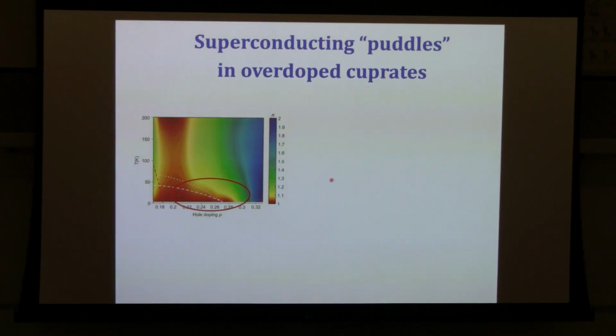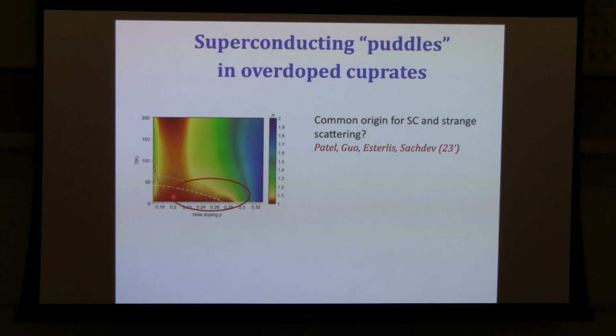The first one is that there's something that's causing the superconducting pairing of electrons, and the same thing is also causing the scattering. This point of view was taken by a recent series of works by Subir Sachdev and collaborators. The idea was that there's some kind of quantum critical point, of the particular type an antiferromagnetic quantum critical point. If our system was perfectly homogeneous, then we would see the familiar fan-shaped strange metallic behavior terminating at this point, and this would be a Fermi liquid.